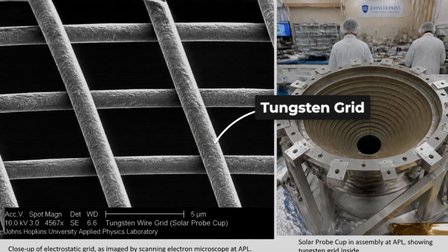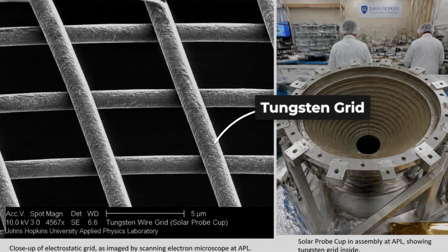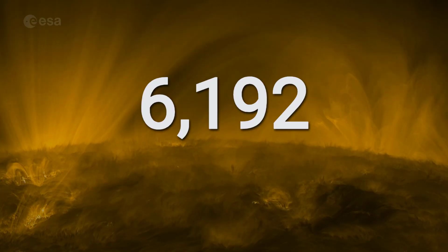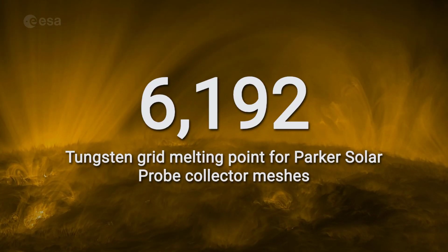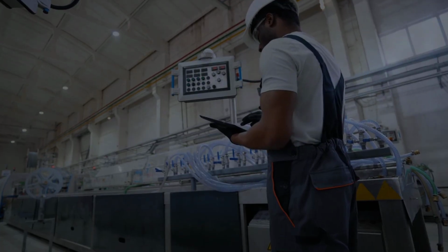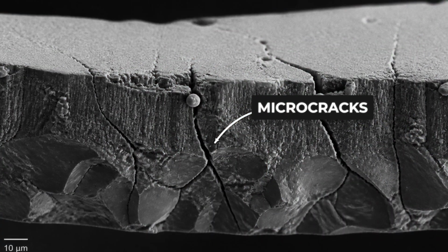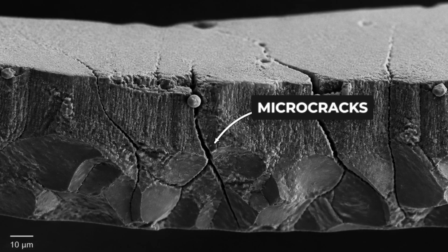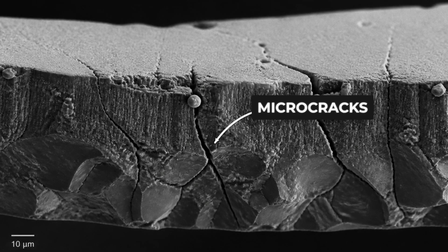Inside, the cup uses electrostatic grids to filter charged particles. These grids are made of tungsten, a refractory metal that melts only at a staggering 6,192 degrees Fahrenheit. But manufacturing these tungsten grids proved to be its own engineering bottleneck. Traditional laser cutting trials failed, leaving microscopic cracks along the edges that threatened to fail under extreme thermal cycling.